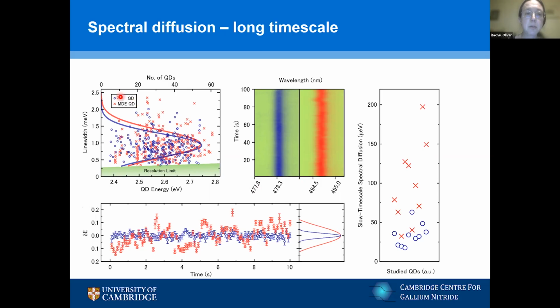I've got both my strain-driven dot growth here in blue and the droplet epitaxy dots in red. In both cases, you can see that compared to the trace I showed earlier, we aren't seeing very many of these huge jumps we were seeing before.